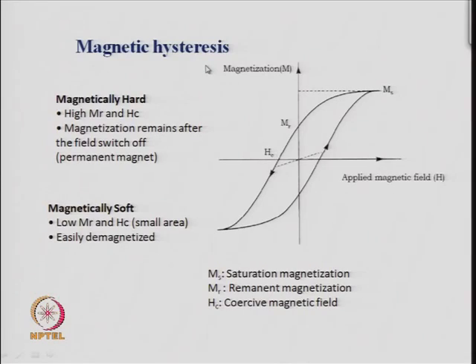So, magnetic hysteresis plots can be obtained if you measure the magnetization M of any material as a function of the applied magnetic field H. So, imagine that you have 0 magnetic field, then the magnetization is 0. So, you are here, and if you increase the magnetic field, the magnetization will increase. Initially it will increase from the origin, it will go like that. And then it will reach a saturation, which is called the MS or saturation magnetization, that is given by extrapolating this line to the y axis, and this value of magnetization is the saturation magnetization.